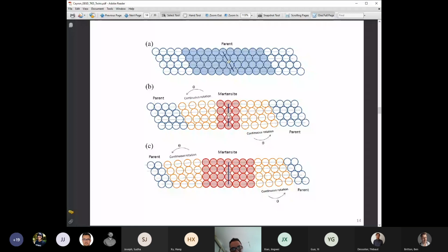So here it's just to tell you that this is the experimental pole figure of martensite, and here is a simulation with the 24 variants and with the continuous rotation A and B. And this continuous rotation fits well with the experiments. And these continuous rotations are actually two important components of the distortion matrix that I could calculate with these simple models made of hard spheres.